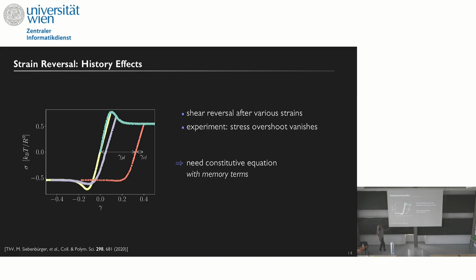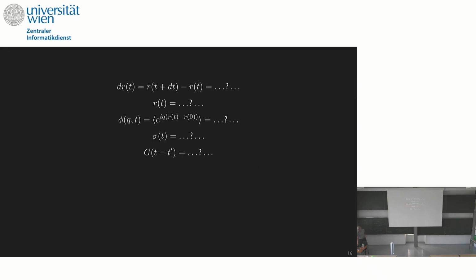And you see that if you do this game reverting at different sections of the shear rate, if you revert anywhere before the stress overshoot, you get a yellow curve. You get something that looks just reversible. And there's a lot to be said about that. Remember the talk by Simon, like the recoverable and the unrecoverable responses and all that. So for my constitutive model, for my modeling approach, it tells me, yeah, even just putting a shear rate somewhere is not enough. I need to really worry about the whole history of shear.